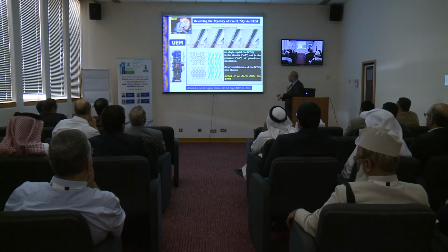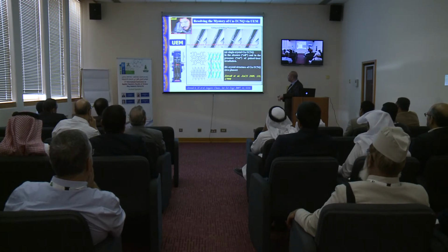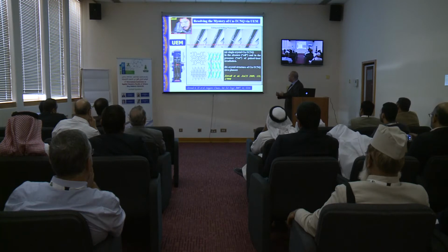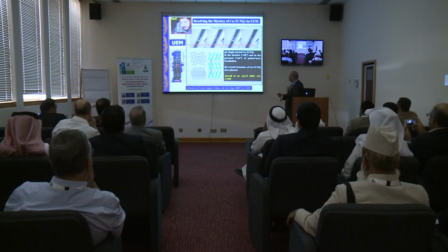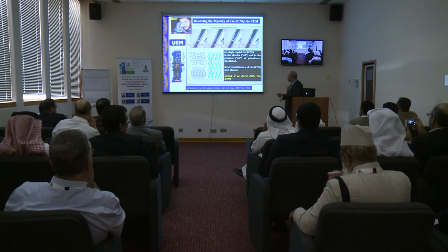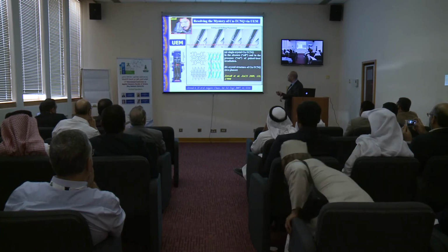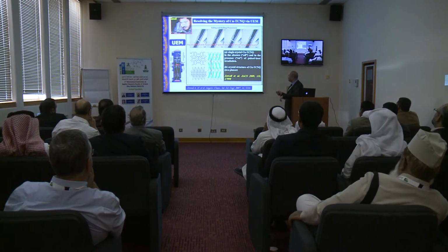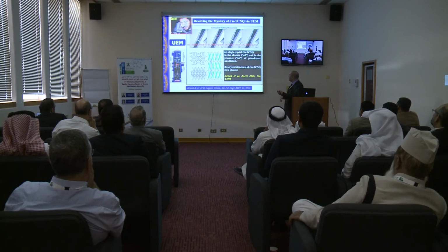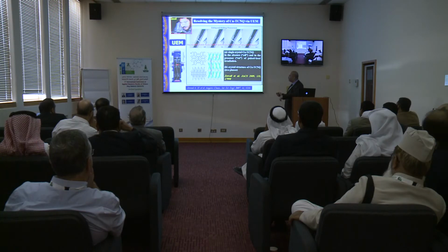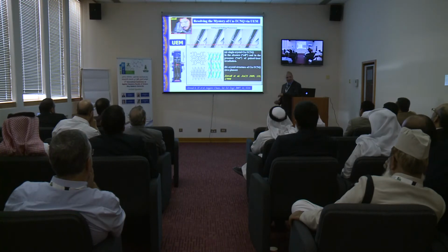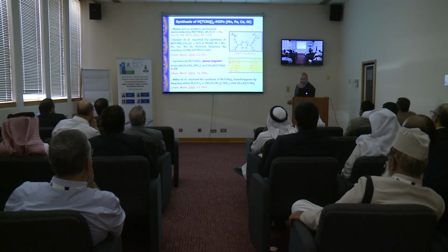However, when you apply light, when you irradiate with light, the crystal expands. As a result, you can see that the crystal starts to become a continuous crystal. So all of these gaps are now filled, and therefore it becomes conducting. So with light on and off, which is applying light or not, you can see the cracks coming back, and that explains why we have this difference: one phase is conducting and the other one is insulating.